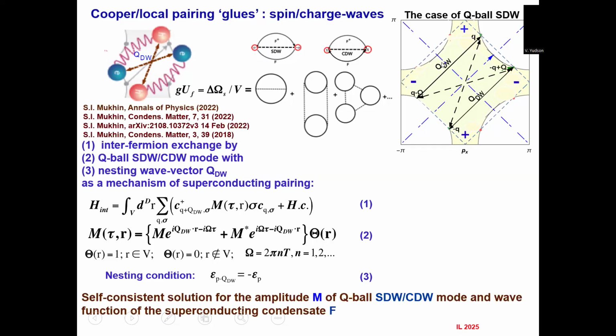So this is the Q-ball density wave, spin density wave. Now, there are other nesting vectors which are between this and this, which prove to be charge density waves. And the anti-nodal points, indeed, are covered with a gap far above TC, and that's why this is the so-called pseudogap. And this is the nodal direction. So this is the D wave order parameter, as we discussed already. You see, this vector really connects the plus region of the D wave with the minus region of the D wave, which is necessary to lower the energy of the Q-ball. And the charge density wave vector, if it forms a Q-ball, would be between these two points. So it would be S wave.